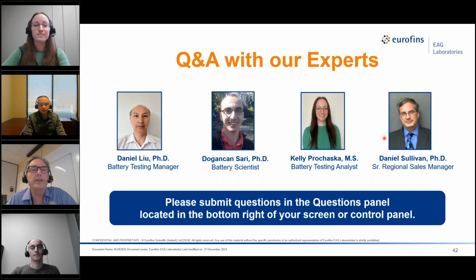Thank you, Kelly. I had another question for you, Kelly. Basically, the question was about what types of defects or what leads to the shortening of battery life and charging time, and are there ways that we can talk about to minimize those effects? Yeah, so there are various reasons for shortening of life and increasing charging time. This would begin from the capacity loss in our anode and cathode degradation. We would begin to see internal resistance buildup. That would be the growth of the SEI layer, electrolyte decomposition, or structural breakdown of the electrodes. This electrolyte degradation would occur due to high temperature and voltage conditions. We'd also see lithium plating when there are excessive charging rates or low temperatures, and separator degradation when there are high temperatures and overcharging. We'd also begin to see thermal runaway due to being overcharged, overheated, or discharged too quickly.